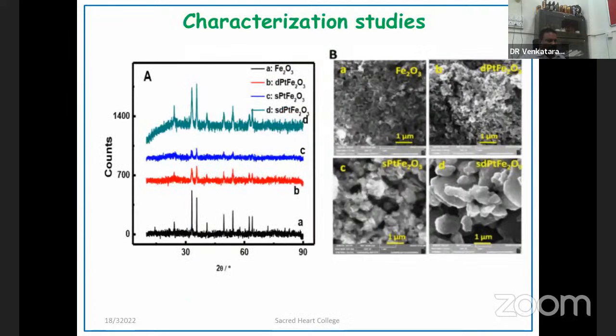Of course, once you develop the material, you characterize it using other supporting physical techniques like X-ray diffractometer or scanning electron microscope. Here we try to understand the formation of the composite between the iron oxide and the platinum. Platinum formation is identified by the appearance of XRD peaks, which are referenced to standard reference data available in the data bank.